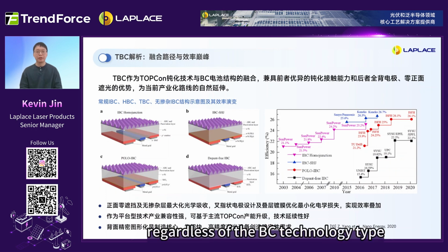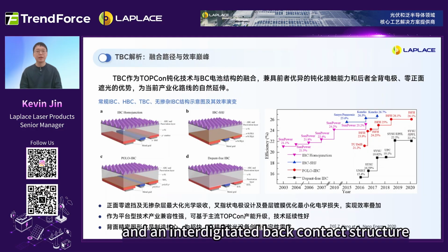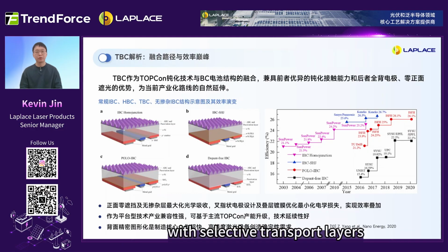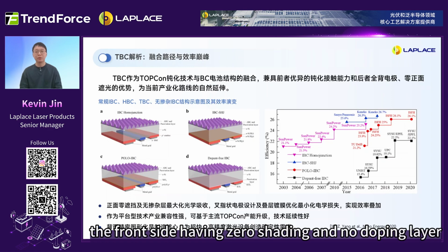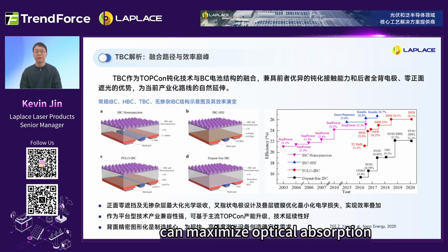It can be seen that regardless of the BC technology type, the main characteristics are no shading on the front side and an interdigitated back contact structure with selective transport layers for electrons and holes. The front side having zero shading and no doping layer can maximize optical absorption. The interdigitated electrode design and optimized stack coating can minimize electrical losses, achieving efficiency superposition.